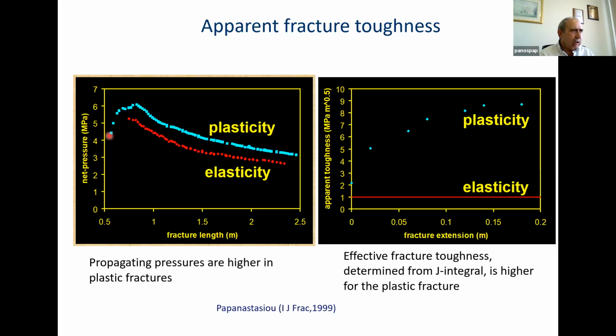What we can see here with plasticity, actually, the net pressure increases at the beginning until the plastic zones are fully developed, and the effective fracture toughness is fully developed at that point, and then decreases like the elastic solution. And here we have the effective or apparent toughness, as we call it, as a function of the fracture extension. It starts, increases the effective fracture toughness, but it reaches a kind of limit value after some propagation steps. With elasticity, of course, the toughness remains constant.